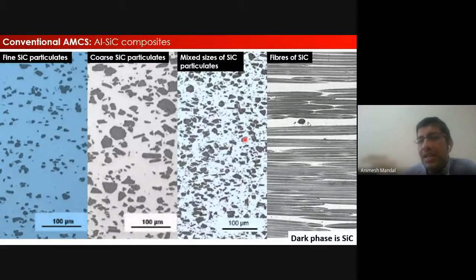For example, in this particular composite, you will have higher properties along the direction of the alignment of these fibers, whereas in the remaining three composites, the properties are going to be more or less isotropic. In this particular case, the properties are going to be highly anisotropic because of the alignment of the silicon carbide fibers. So all of these four composites shown here are aluminum silicon carbides, but all of them have different microstructures and you can generate different kinds of properties.